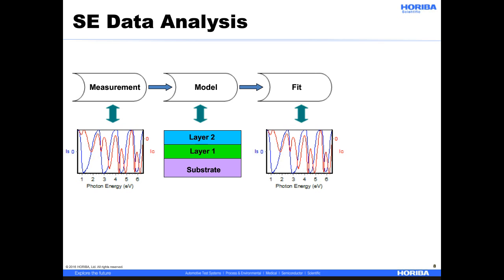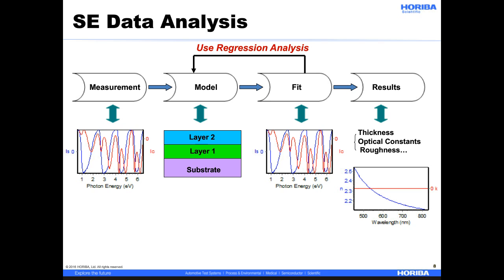And then we do a fit and check how well that model fits to the data. We use a regression analysis, make some changes to the model, and keep doing the fit until we get a good fit. And then you end up with the results - your thickness, optical constants, roughness.